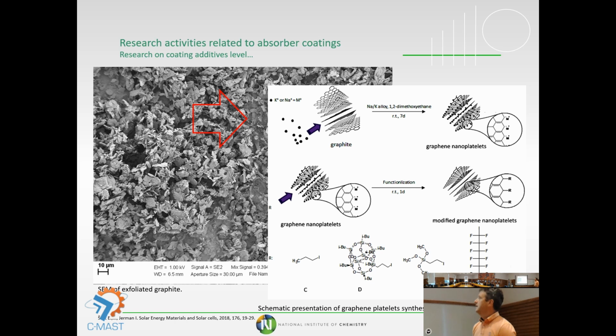But we published some work where we modified the graphene nanoplatelets with different molecules in order to make them easier to incorporate, because quite often for high temperature applications we are using a silicon-based binder, which sometimes is not a good host for the particles. So we tried to modify with different molecules and to show in the end that we improve the dispersion.